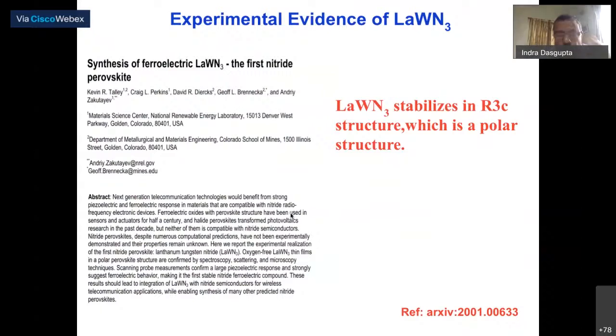So this was, of course, a theoretical prediction. After a paper came out, we saw an experimental report of this system. At least this system has been synthesized. Nobody has measured its ferroelectric polarization. I hope this will eventually be measured, and possibly the prediction of the Rashba effect will be verified in this system.